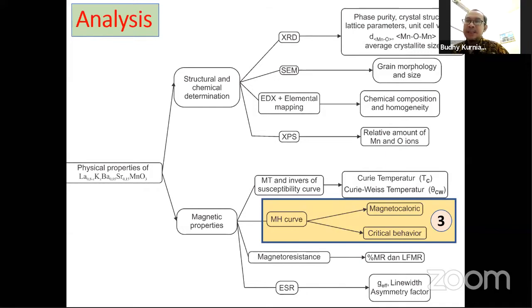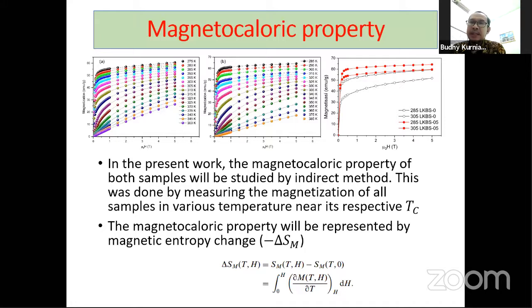Another magnetic properties analysis is the M-H curve, and this is the main part of our work here. From this we can get the magnetocaloric effect and also critical behavior. Next, please. This is our magnetization process measurement, M-H, with the magnetic field from 0 to about 5 Tesla. We measure at about 20 or 21 temperatures, ranging from TC to the upper temperatures and also to the lower side of TC.